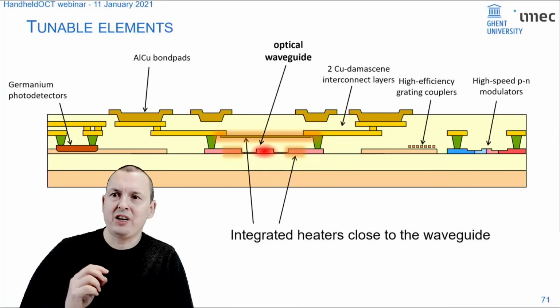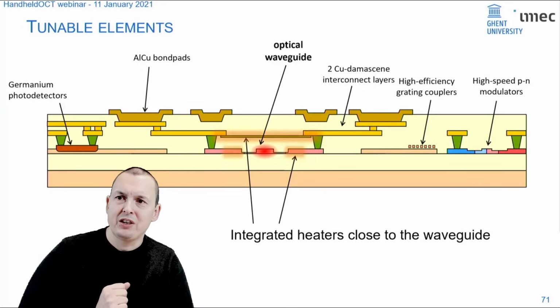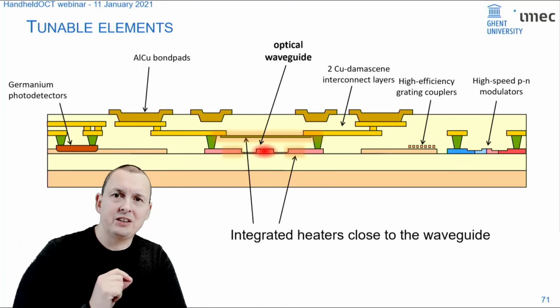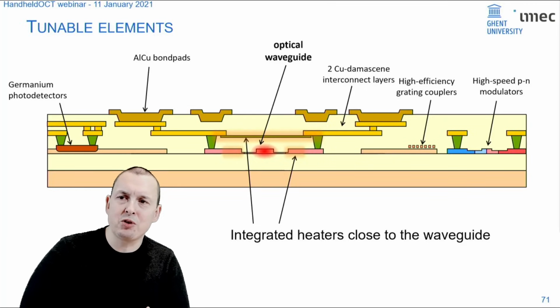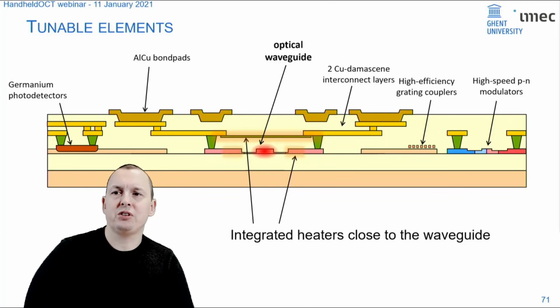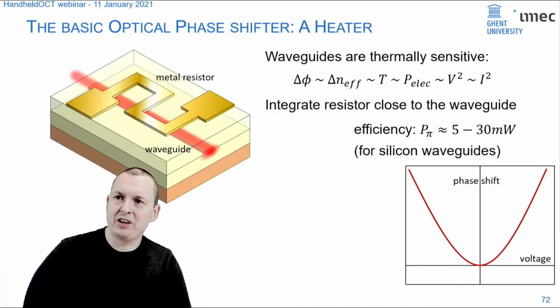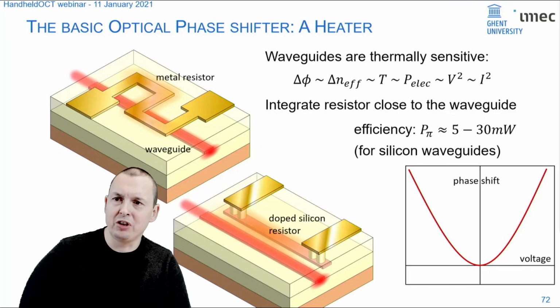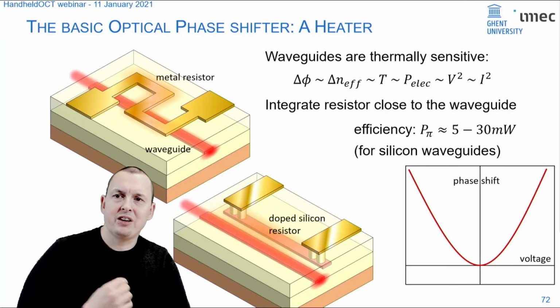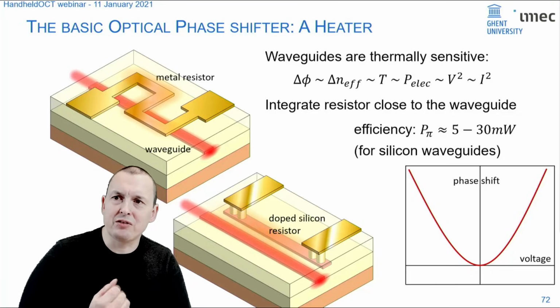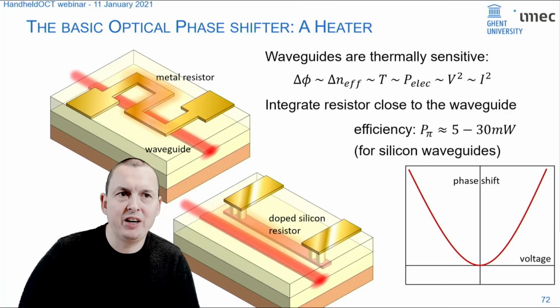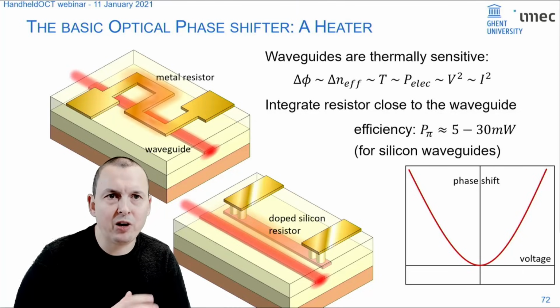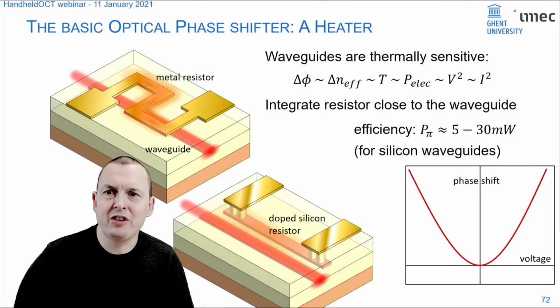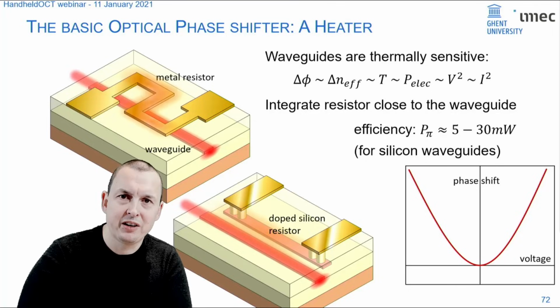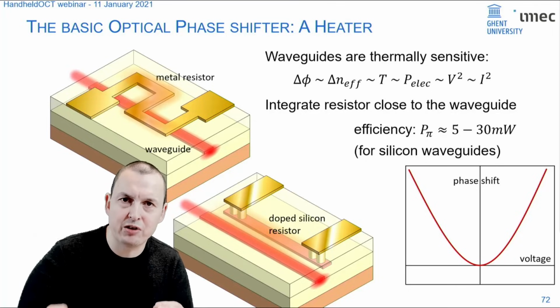Now, on top of that, you also have integrated heaters. These heaters are not really used for fast modulation, but they are used to tune the optical behavior of your waveguides. So you can, for instance, implement a phase shifter by putting a heater on top of it. And because all these materials are temperature sensitive, the effective index of the waveguide will change. You can also embed a heater, for instance, next to the waveguide. Now, heaters have the advantage that they're really easy to make. I mean, you just need an electrical resistor somewhere close to your waveguide.